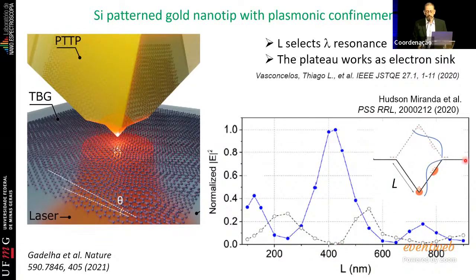And this plateau here is very important because you are entering resonance, not with this pyramid as a resonator, but because of this plateau, you can think of image charge in electromagnetism. And this acts actually as if it was, let's say, a pyramid shape like this, but with a sink of electrons that is very effective. And this is why you have a very high peak here. And if we had just a pyramid like this without this structure, the resonances we would have would be those. And this gain here in efficiency, and what we are imaging here is the intensity of the field at the very edge of the structure. This gain in efficiency makes this tip very, very good, okay?